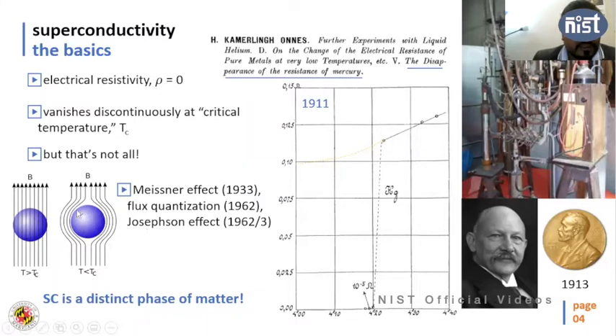So if you consider this blue sphere is a metal, and you cool it down to a temperature below 4.2 Kelvin, what happens? These metals, basically the superconductors, do not allow any magnetic field to pass through the material. And the same metal, if you put it at a temperature just above 4.2 Kelvin, the magnetic flux can pass through this material very easily. So what happens below 4.2 Kelvin is that this material becomes a perfect diamagnet. So it repels the magnetic flux passing through it.